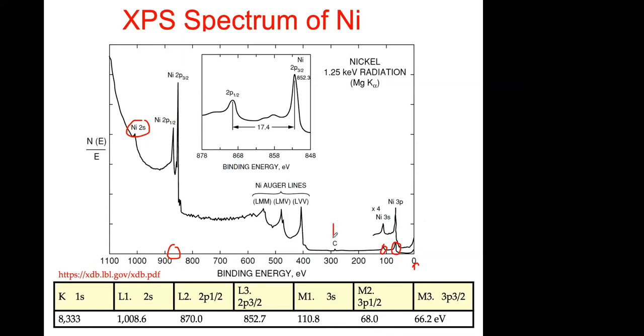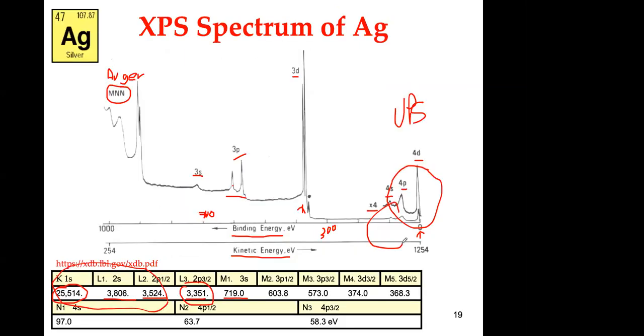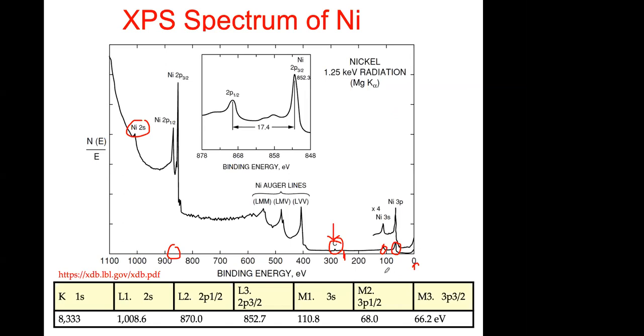And then this that I mentioned before, usually you have a carbon signal. This surface was not clean enough, and you see a peak, and this peak sometimes is taken as a reference. So this I don't think was corrected actually, because it's 250, so maybe it's not corrected. It's pretty close to 300. So that's why probably you see this, because this is sort of the external levels. Oops, it should be closer to zero.